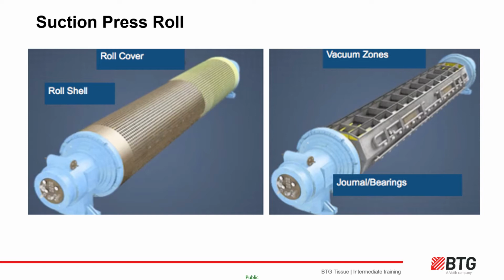The roll shell is covered by a polymeric roll cover, for example polyurethane or other rubber compounds. A hard roll cover offers higher nip pressure, better dewatering and higher tissue strength. A soft cover offers lower nip pressure, longer nip contact with higher tissue bulk and thickness, but better compatibility with the Yankee. Each press roll cover is pre-ground to match the crown on the Yankee when it is at full steam pressure. These roll covers also must be hard wearing and resistant to external and internal forces, to heat and also to chemical degradation from process and cleaning chemicals used on the paper machine.